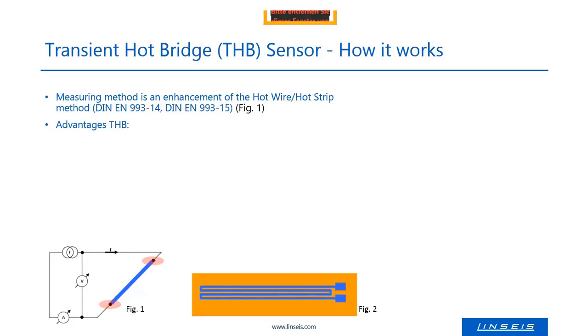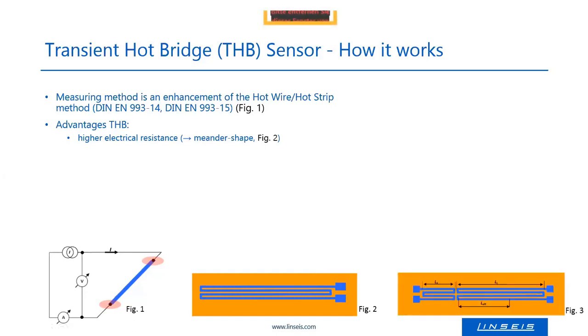to make this possible. So here is how the sensor looks. This is one heat wire or heat strip. You can see it is folded a couple of times, and it's what we call a meander shape. And this meander shape increases the resistance because the wire is longer, and also the change of the resistance during the measurement will be higher. So the signal will be higher with a longer wire.